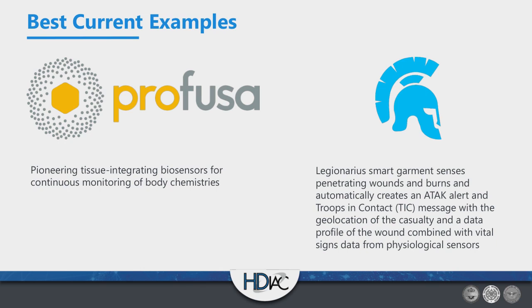So two current examples I want to talk about that I think are quite interesting. One is Profusa. They had some initial funding from DARPA, and they developed the sensor. It's about 5 millimeters long, 500 micrometers in diameter. It's a soft, flexible fiber made of a porous gel, and it mimics the environment of cells, and it's embedded into tissue. And what it does is it emits a fluorescent signal whenever it's in the presence of a biomarker like glucose, lactate, or oxygen.